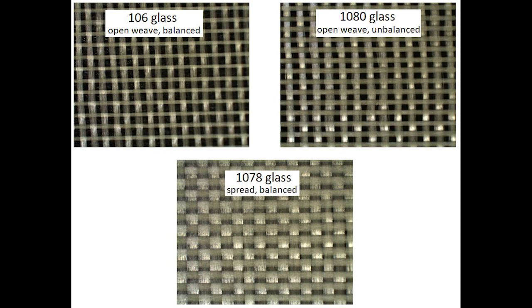The term of balanced and unbalanced refers to the glass density on the x-axis compared to the y-axis. So it does not necessarily mean the geometry of the glass bundles are the same on one axis versus the other for balanced. It means how much glass density is on one axis versus the other. And then finally, the bottom picture of the 1078 glass, that's a spread glass, and that's also considered balanced. You can see in the case of the spread glass, there are no openings, and that can be very advantageous for avoiding issues with the glass weave effect.